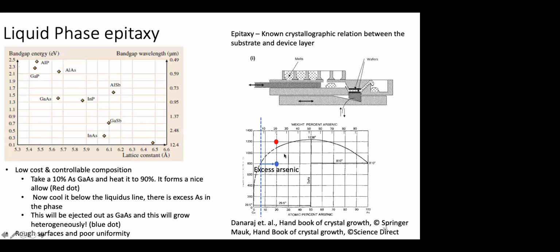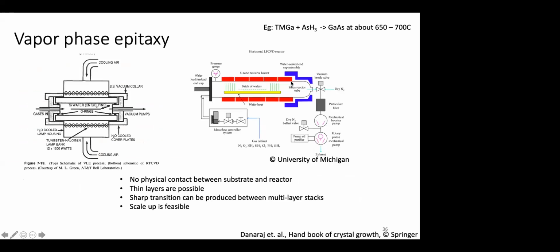One way is called liquid phase epitaxy, which many people have already done. So you have already seen the Czochralski method. You have a melt and you insert this single crystal substrate right below the melt. And when you have something like this, you form what is called an alloy. And when you reduce the temperature of the alloy, it will segregate. Depending upon the percentage of each of these materials, it will solidify. So you have different melts. For instance, if you want to grow aluminum gallium arsenide on top of gallium arsenide, you have an aluminum gallium arsenide melt here. You put a gallium arsenide wafer below, and the aluminum gallium arsenide will solidify right above this. This is the way you grow liquid phase epitaxy.